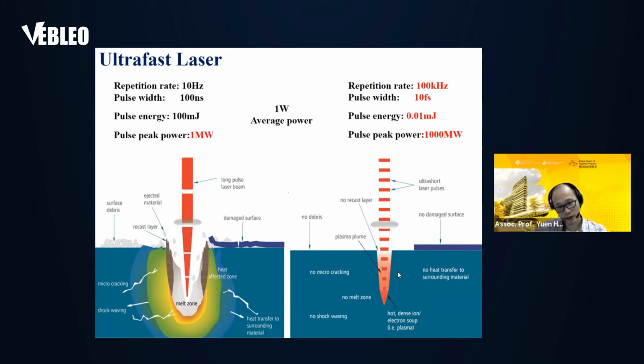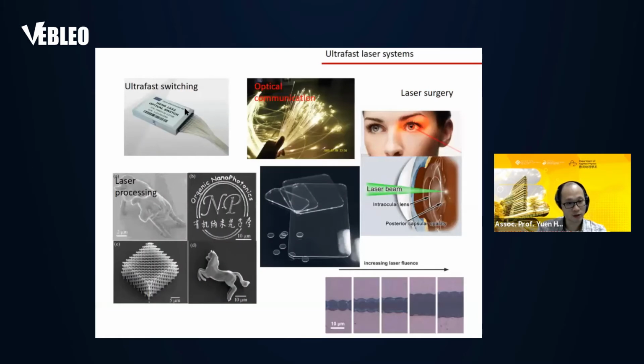So that's why when we're using this ultra fast laser for cutting and laser processing, we can actually make a very smooth edge, as you can see from there. For example, those high-end electronic devices, iPad, iPhone, sort of like a screen. That smoothness will allow a stronger bending force the screen can withstand, for example.